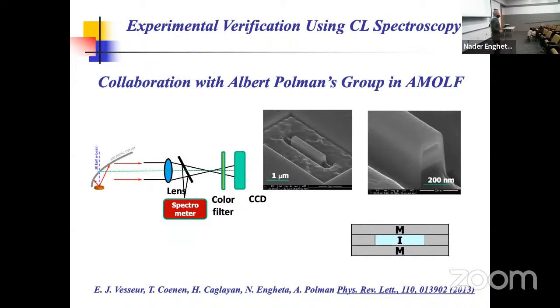You notice that this waveguide is the visible analog of the microwave waveguide that I showed you. This is only 2 microns in size over here. The rectangular waveguide has silicon dioxide inside, it's covered with silver, and with the focused ion beam you cut the two ends of it. So essentially, it's a rectangular waveguide in the visible domain. We made several of them in Albert's lab with different widths. The height of this region is 85 nanometers.